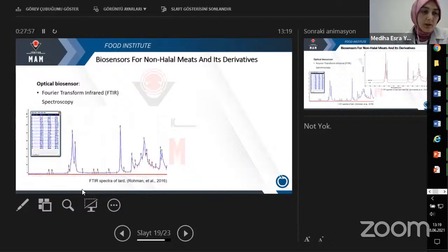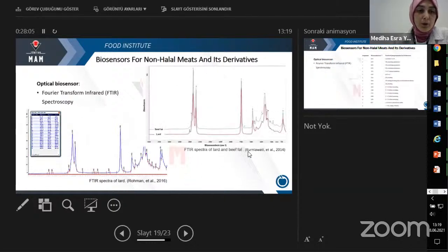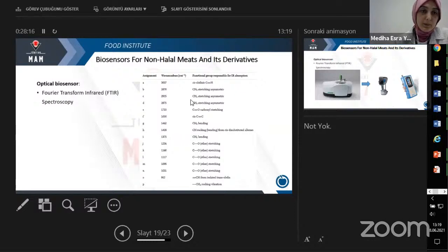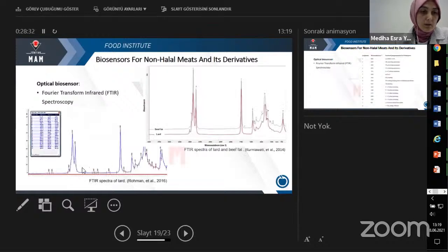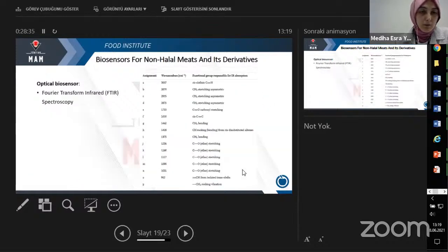In a study, they had the FTIR spectra of lard, and they have this nice spectrum. And in another study, they compared it with the beef fat and found out the differences between the beef and the pork. Each wave number specifically indicates the functional groups responsible for the absorption. So it is evaluated this way. And at the end, with the help of statistical methods, all these spectra become meaningful.